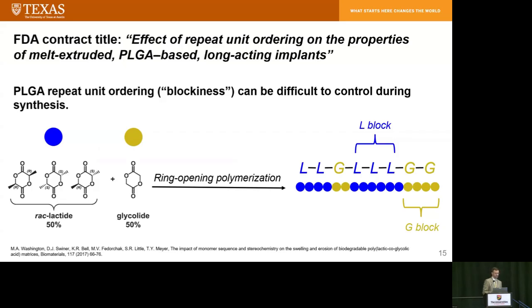During the PLGA synthesis, they start with the monomers, which are actually the dimers, lactide and glycolide. And glycolide is actually a little more reactive than lactide. What this means is that early on during the synthesis reaction, the glycolide is consumed faster, meaning that the growing polymer chains have more glycolide units, so more GGG units in the polymer chain. But then as the synthesis process continues, the glycolide is less abundant in the reaction vessel. There's more lactide now. And so later on in the synthesis reaction, you get more lactide, so you get LLL blocks.